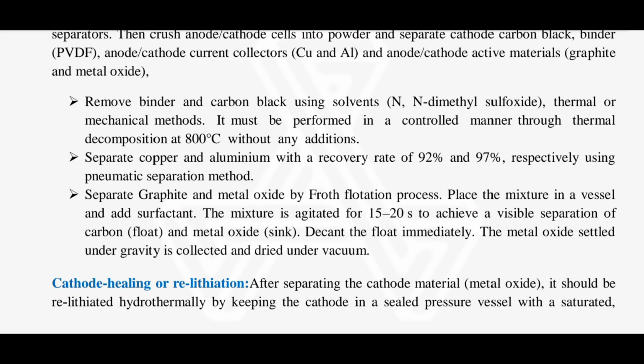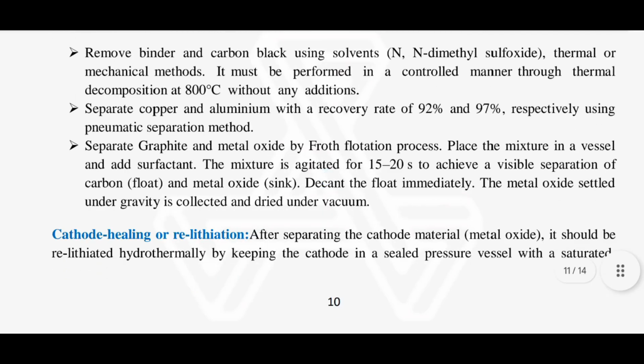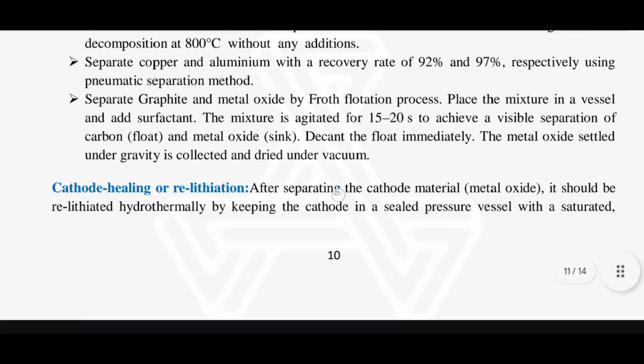It must be performed in a controlled manner through thermal decomposition at 800 degrees Celsius without any additions. Separate copper and aluminium with a recovery rate of 92% and 97% respectively using pneumatic separation method. Separate graphite and metal oxide by froth flotation process.